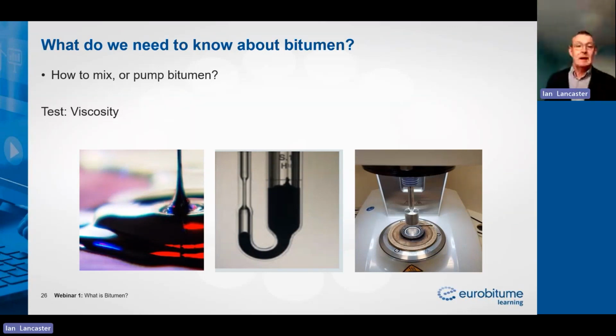Now, we have two different methods of assessing the viscosity of the bitumen. We can use what is called a capillary viscometer here, and we can measure the viscosity at some precisely defined temperatures, either 135 or 60 degrees. These are the oldest, and they tend to give us only very discrete information. So they can only give us information of the viscosity under precisely defined temperatures.